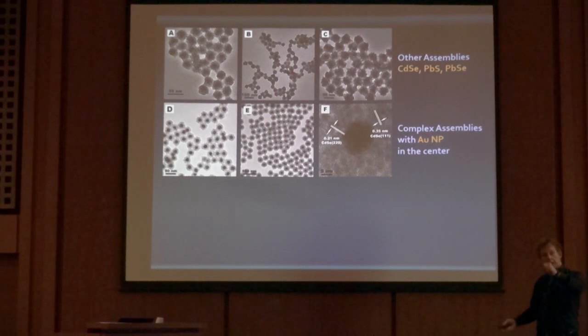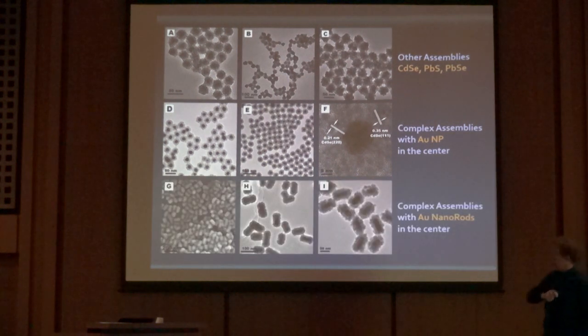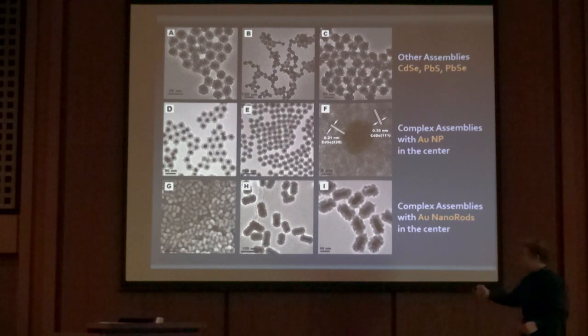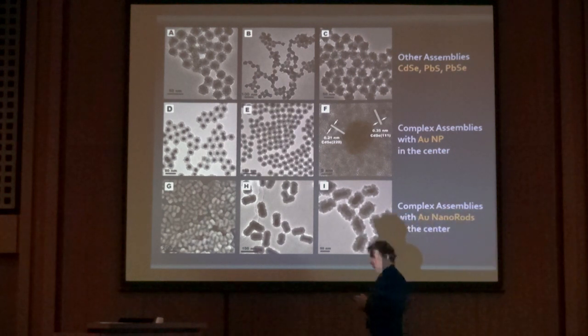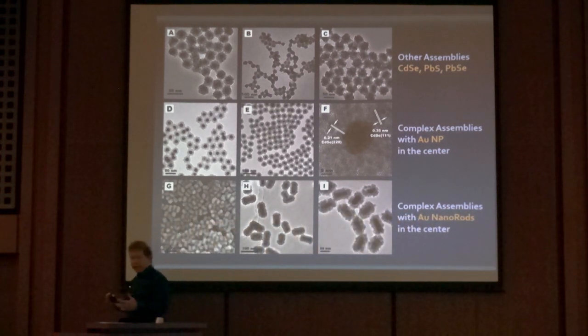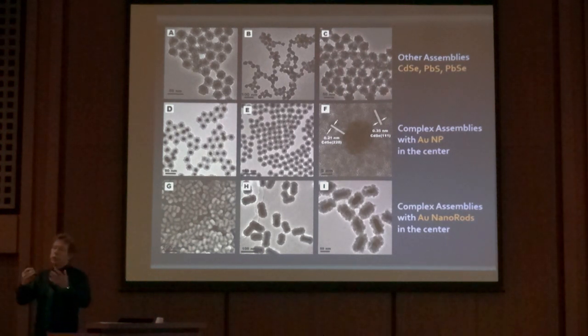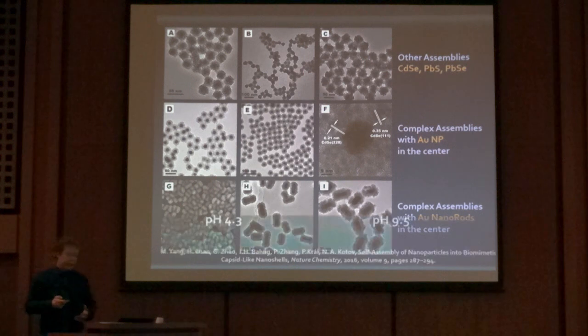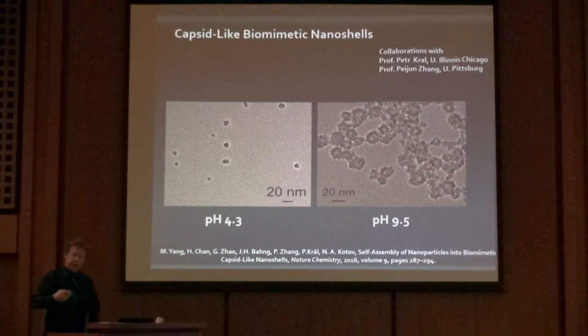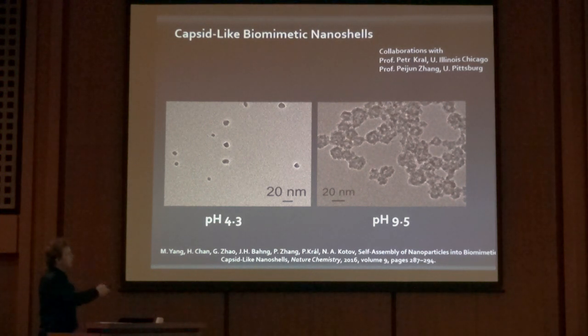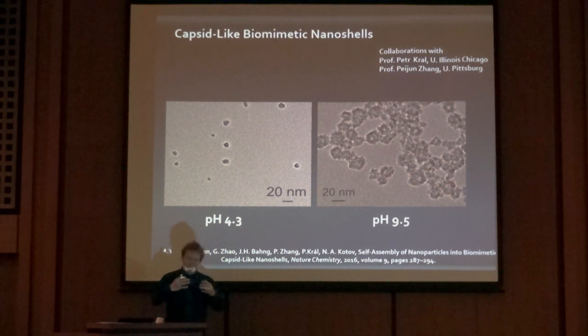So we start with gold, it has the negative charge, we add other particles which have the negative charge, and they're attracting, forming this kind of clusters of virus-like shells. We were looking for other systems which could provide better choices and better engineering approaches for our colleagues in catalysis. And we found the assembly conditions when the particles form shells. The shell conformation here is essential because when you have the empty space inside, you can carry out the chemical transformation in much easier and much more efficient way.